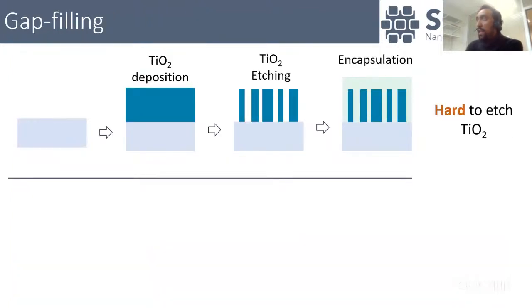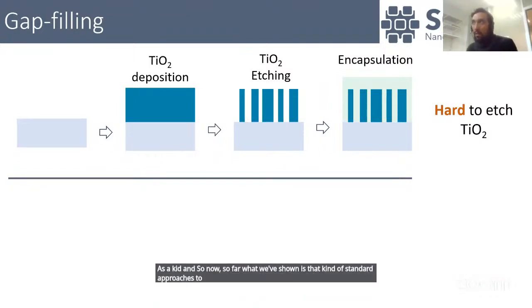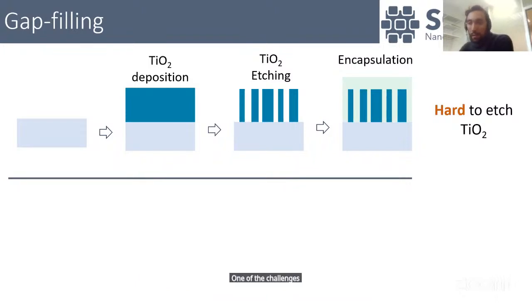This is key. So far, what we've shown is the standard approach to make metasurfaces. Basically, you start with a thick layer of the high refractive index material, you etch it, and then you do the encapsulation. One of the challenges that a lot of customers today have with etching TiO2 is that it's a difficult material to etch. So they have to come up with very slow etching processes. Sometimes they use atomic layer etching, which is quite slow.